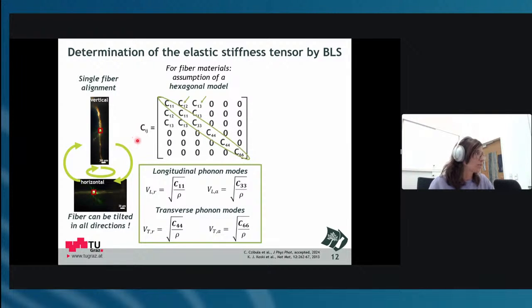And then we needed to assume a hexagonal model for the fiber. This is very common. Fiber materials are usually described by the hexagonal symmetry. And that's how this elastic stiffness tensor looks for such a symmetry. You have here the diagonal field with C11, C33, C44, and C66. And these diagonal components you can directly measure with Brillouin. So ideally you get all the stiffness tensor components in the diagonal from the measurements. And then you just need to determine C12 and C13. We will come to that later.